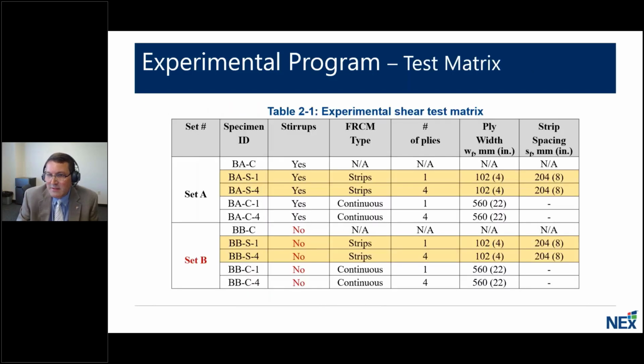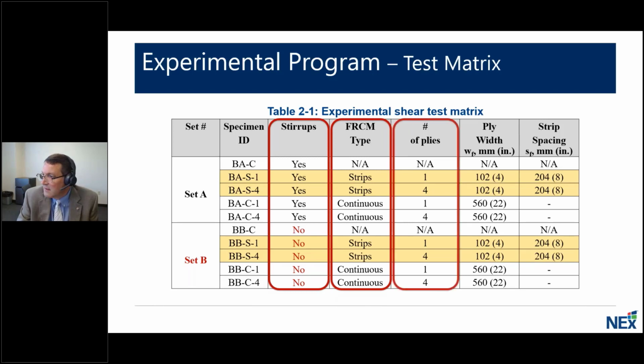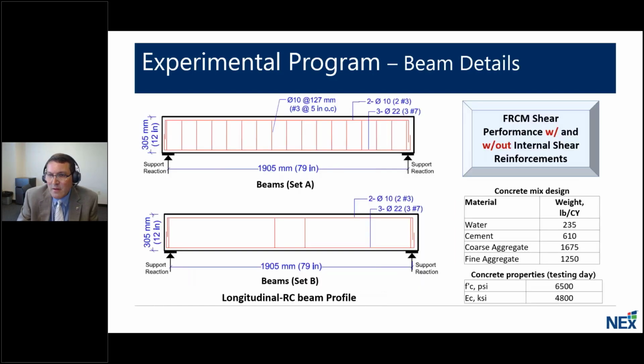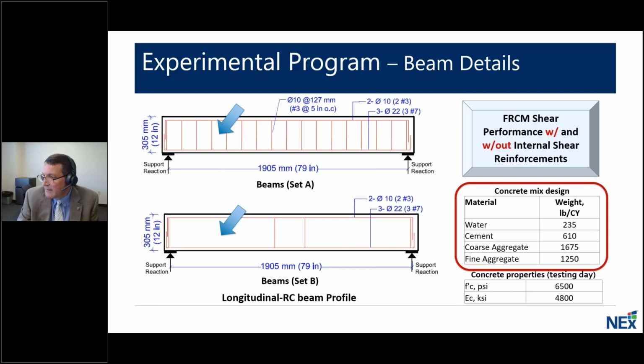In this work, we examine the behavior with and without steel stirrups, as I mentioned earlier, and we also looked at the type of shear reinforcements, continuous versus using strips, as well as the number of plies, 1 versus 4. Here is shown the profile of the beams, first with internal steel reinforcement, as well as without. Again, the mix design that we used was representative of what we would expect in the field for an older structure that would be a target structure for repair.